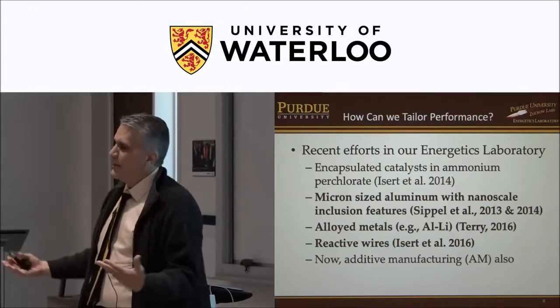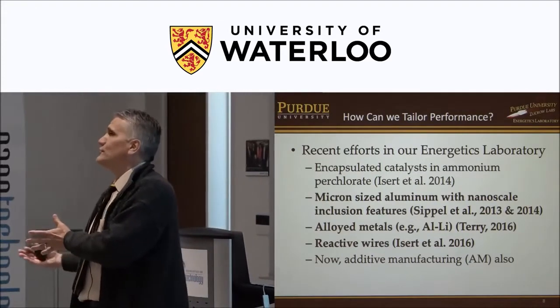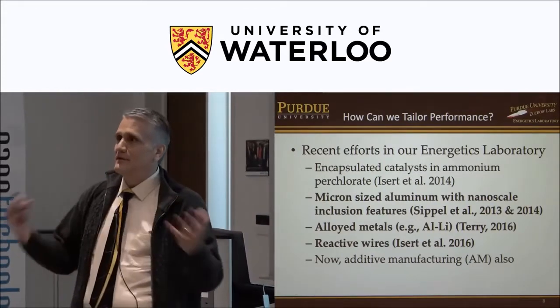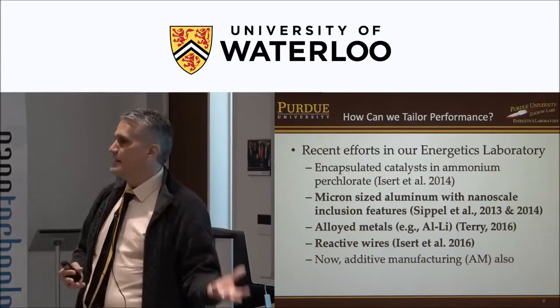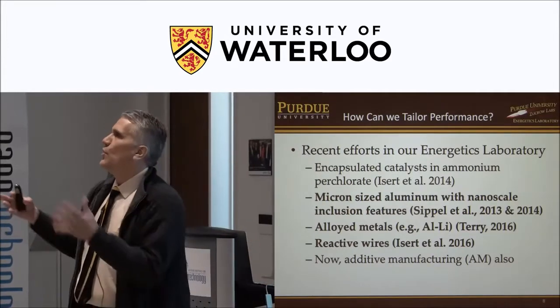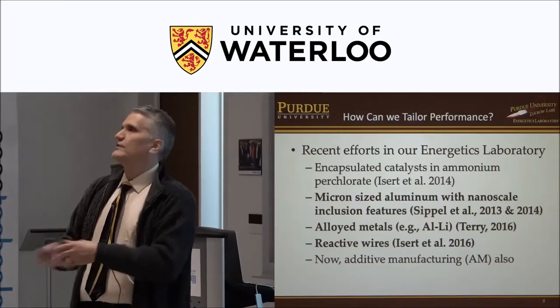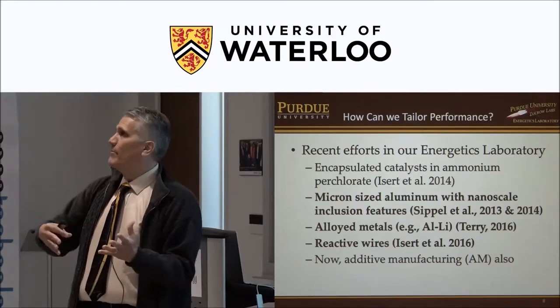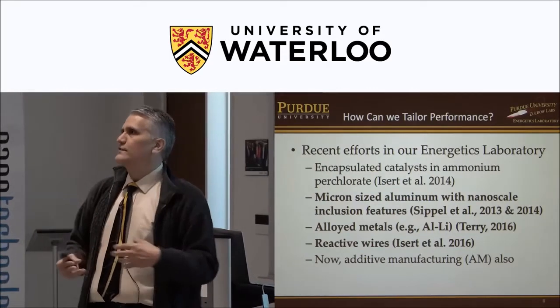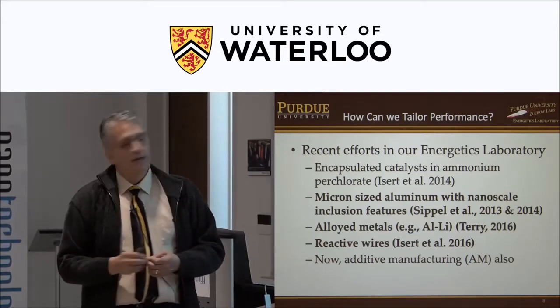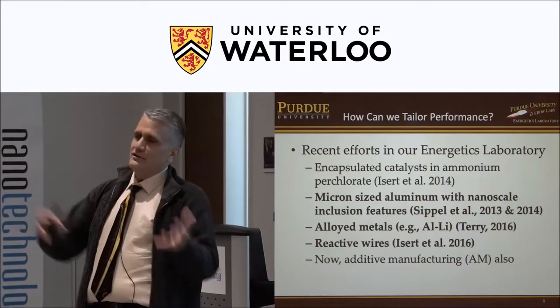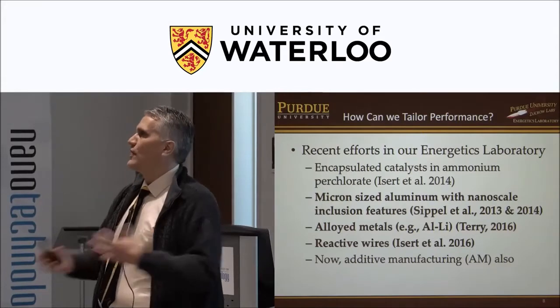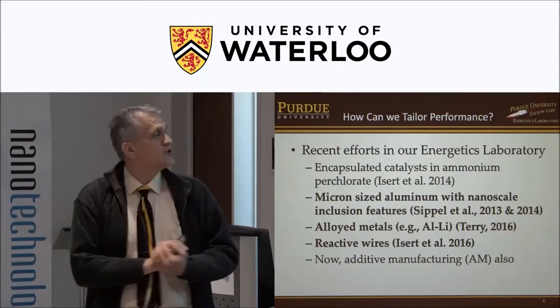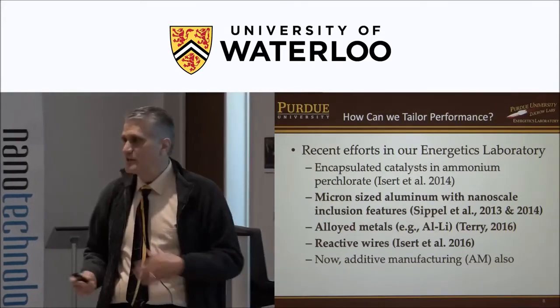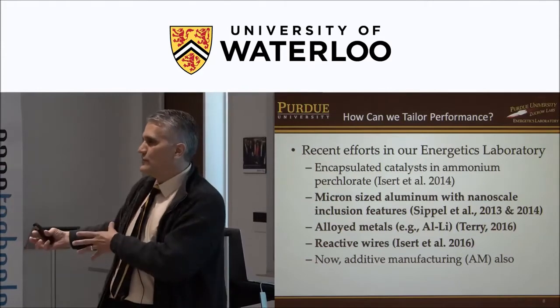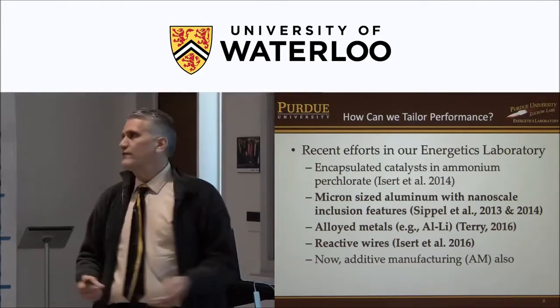And if you bring in catalysts, you want high surface area. They work better if you have more surface area. So you like the nano size, but if you want to put that into your propellant, you have to sometimes add more binder if it's a really high surface area catalyst. And you don't want to do that because you're starved for oxygen already. You're trying to bring in as much ammonium perchlorate as possible. So to bring in a really high surface area catalyst, you have to sacrifice performance.